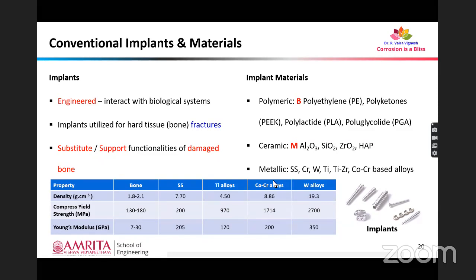For instance, we could see cobalt chromium alloys. The density of bone is 1.8 gram per cc, but cobalt chromium has a density of around 8.86. Their compressive yield strength, which for bone is around 130 megapascals, is around 1714 megapascals for cobalt chromium. And Young's modulus is going to be 6 times higher than that of the bone in cobalt chromium alloys. Generally speaking, all these conventionally used metallic materials have very high density, very high compressive strength, and very high Young's modulus than that of the bone.